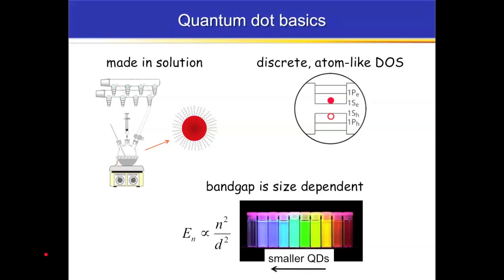And so you have a particle-in-a-box type physics. And you've got energy level separations that depend inversely in some fashion on the diameter, and often to the square of the diameter. So the smaller the quantum dot you make, the bluer the absorption and the bluer the emission is going to be. That's because the HOMO-LUMO gap or the band gap is larger in that case. And this is the very famous picture for cadmium selenide dots.